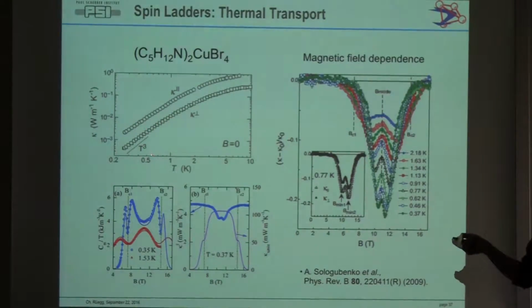In this case, let's say, in the other 1D materials, the energy scale is such that in terms of temperature scales, you see two peaks, and they are at different places. That's very helpful, and you have the anisotropy, which helps. So you can subtract the phonon contribution, which is assumed to be isotropic, and you have the spinons. In this case, the energy scale is two orders of magnitude lower, so everything overlaps, and there's only weak anisotropy. So, as I said, maybe it's not the end of the story in this business.